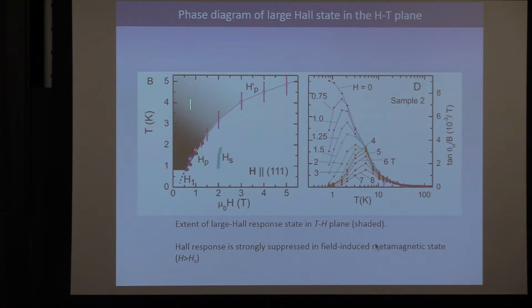So one way to show this is in the phase diagram, field versus temperature. And so the experiment is done by holding the temperature and sweeping the field, right? So making cuts like that. And you can see that this interesting phase gets progressively narrower as the field-induced effect kicks in. So it's again, yeah, it looks like it remains there at 0 Kelvin. And these curves are cuts at fixed field going vertically. So you see that there's this very large Hall angle response in the sample.